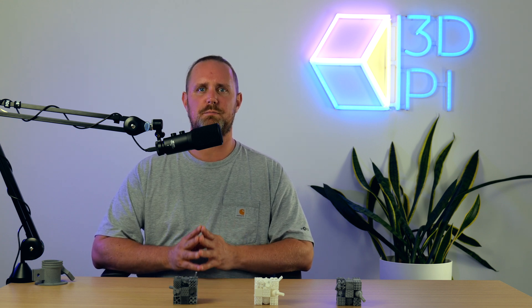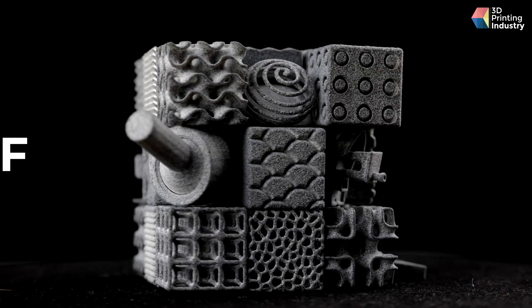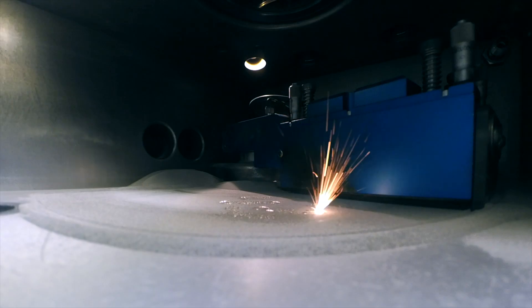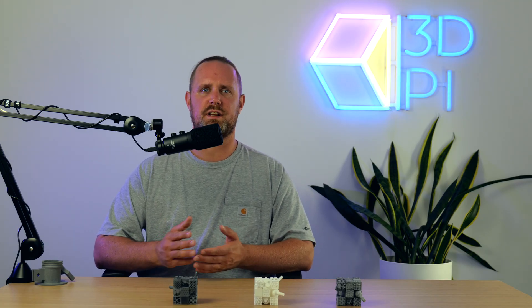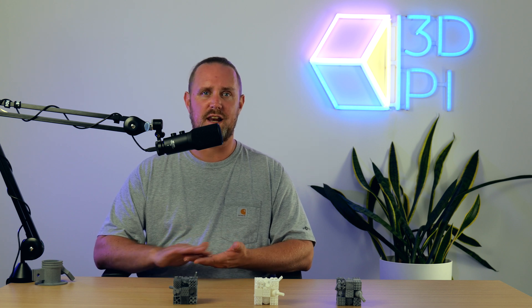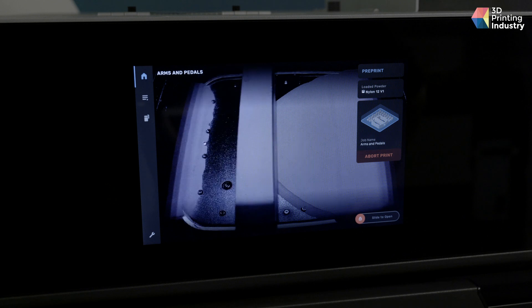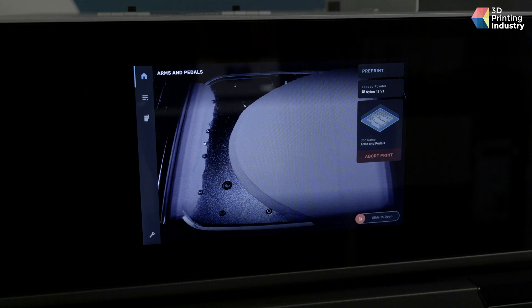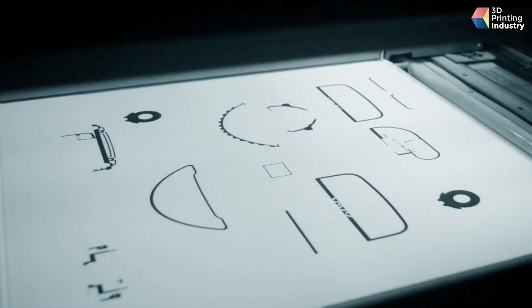In this video, we're looking at three powder-based 3D printing processes: High-Speed Sintering (HSS), Multi Jet Fusion (MJF), and Selective Laser Sintering (SLS). All three methods use powder materials — the difference is in the binding process. SLS is a powder bed fusion additive process: the laser sinters powder material in a heated build chamber. Layer by layer, the part is built up. After each layer is lasered, a re-coater system — maybe a blade or a roller — spreads another thin layer of fresh powder and the process repeats.